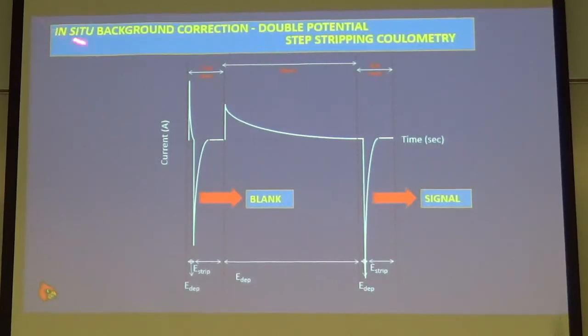So what Mohammed Mareh developed is a technique called double potential step stripping. And it has four pulses. First, we apply a reducing potential that's very, very short. At that potential, the copper or the metal could get deposited, but that only lasts less than a second. So only a very small fraction, less than 1% of our copper, actually gets deposited. Then we step the potential back to do a stripping experiment, but there hasn't been much metal deposited, so that stripping is the background. There's no copper involved here.